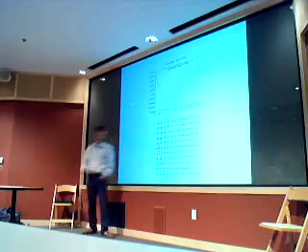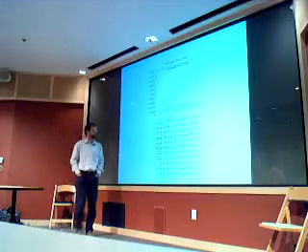These sudden drops in the total energy, associated to the increase in the number of basis functions, interfere with the minimization process that we want to do.